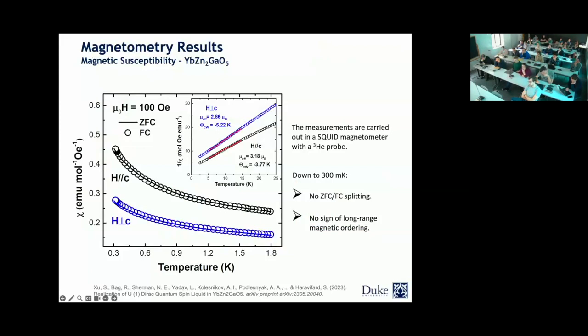In a triangular lattice, one way is to look at it at very low temperatures. So you're looking at the DC susceptibility as a function of temperature, and this was done down to 300 millikelvin at Duke. We were able to look at the two different orientations for the field, and none of them show any features indicating ordering down to 300 millikelvin. We also did zero field cooling and field cooling. By doing that, you can figure out if there is spin freezing, because if it starts to show a hysteresis, it means you have spin freezing. We were not able to see that down to 300 millikelvin.